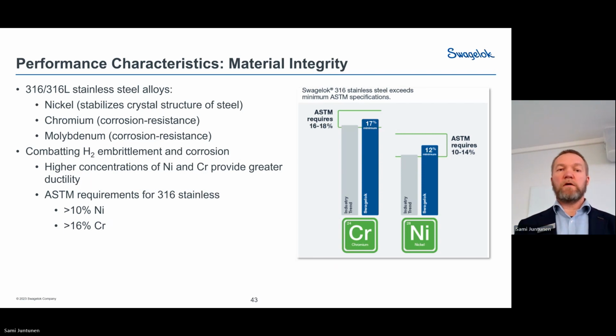And that nickel content is very important for hydrogen embrittlement. So when we have 12% nickel content in stainless steel, it will be a much more embrittlement resistant material, and that helps against embrittlement. Because every time we're talking about stainless steel in any grade, there is an embrittlement possibility. It takes time and pressure, but it happens. But with a certain nickel content, we can avoid it as much as possible.